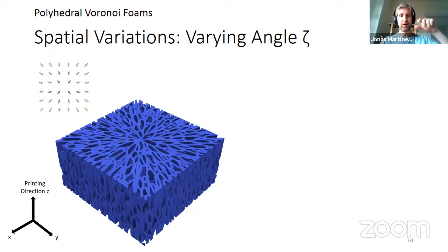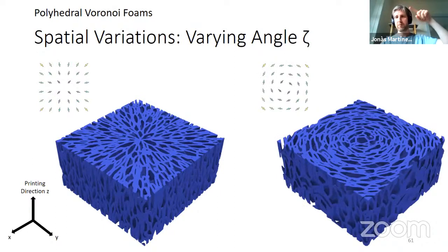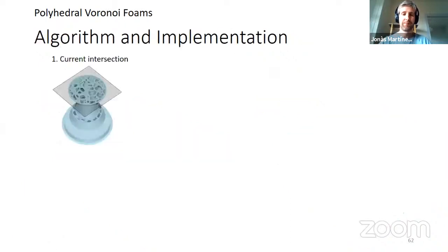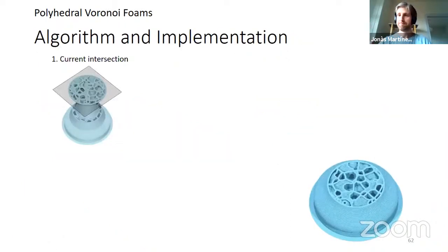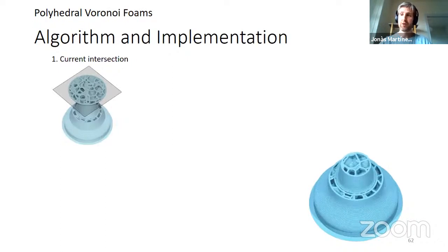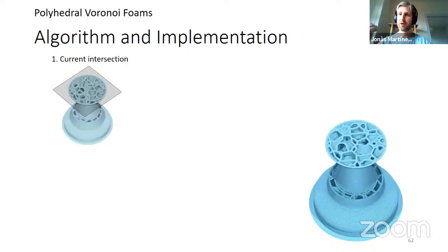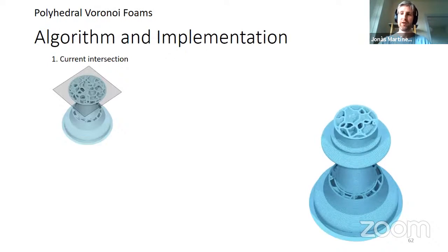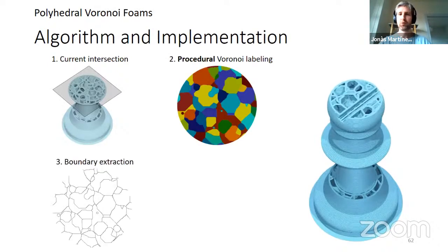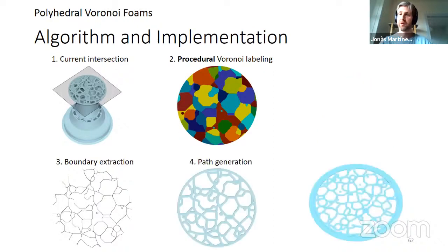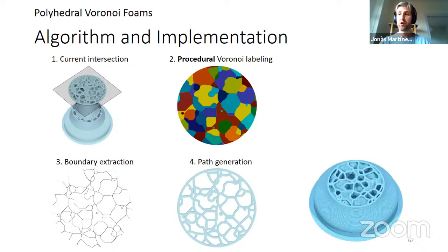And that's one of the things that we like most, that we can control also implicitly the angle. So here you have a concentrical pattern, and you can see that you get a structure that is concentrical. And here you have the same, but in the orthogonal direction. And what I want you to remember again is that all these structures remain printable with a fused filament fabrication machine. And again, we do that in a procedural fashion. So this is basically a program that procedurally evaluates for each point to which Voronoi cell it belongs. So we do a procedural labeling and then also a boundary extraction. And we generate directly the G-code, never a mesh.